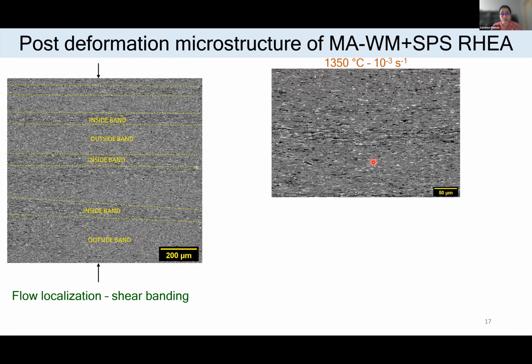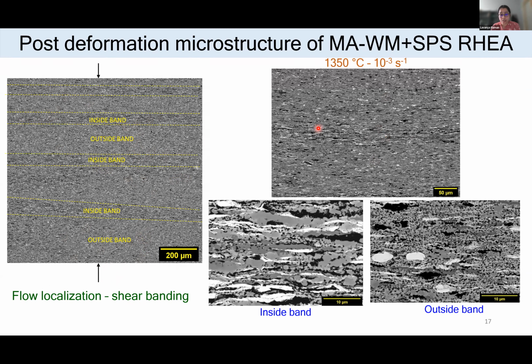When we look into these bands closely, I have shown the SEM microstructures here separately for the inside band and the outside band region. We can say that all the phases have deformed, but the extent of deformation of these phases is more in the inside band region. That is, these bands take up more of a strain compared to the other region.